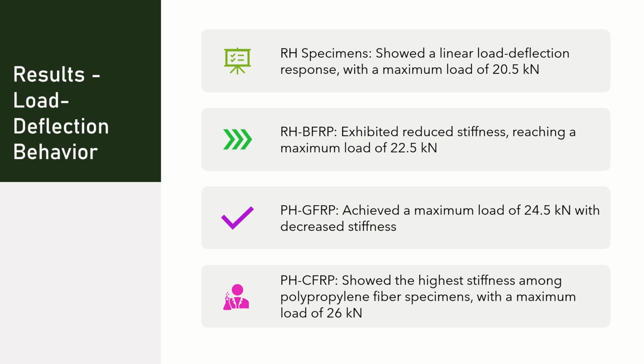As you can see, here are the results for load deflection behavior. For the non-fiber specimens, the RH specimen showed a linear response, reaching a maximum load of 20.5 kN. The RH-BFRP specimens had reduced stiffness but reached a maximum load of 22.5 kN. For polypropylene fiber specimens, PH-GFRP achieved 24.5 kN, although with decreased stiffness, while PH-CFRP had the highest stiffness among them, with a maximum load of 26 kN.